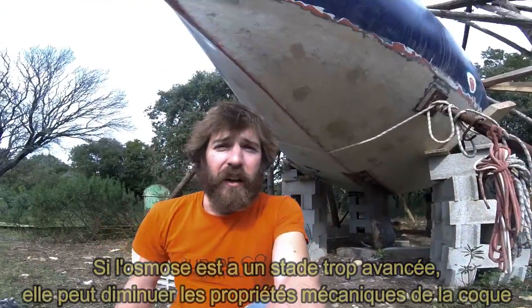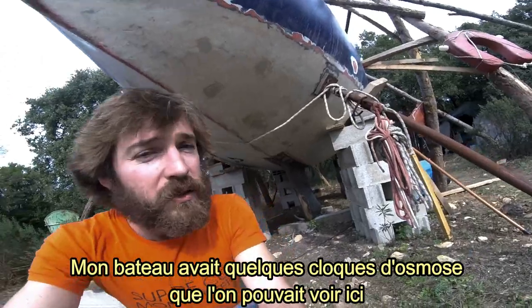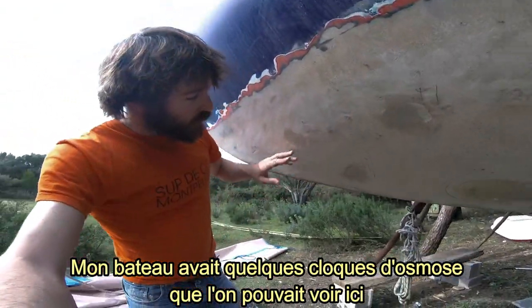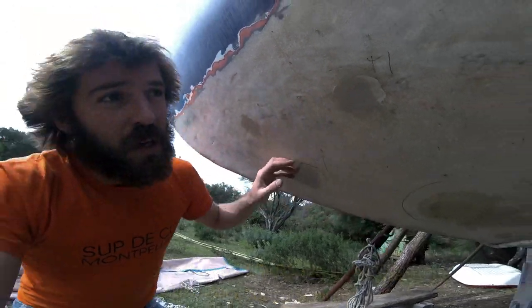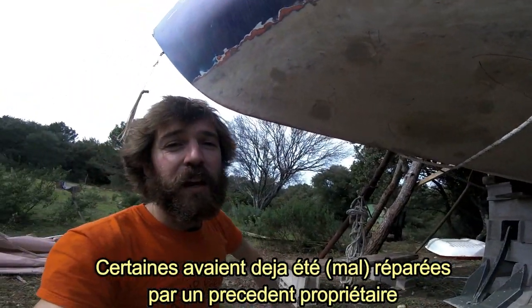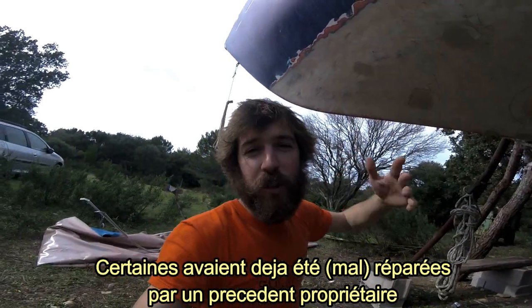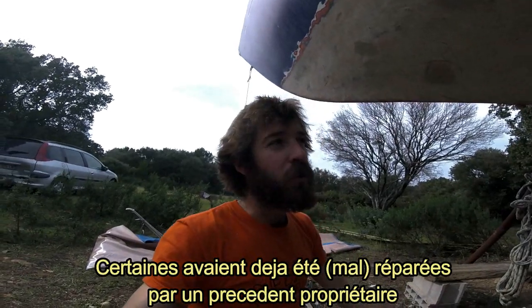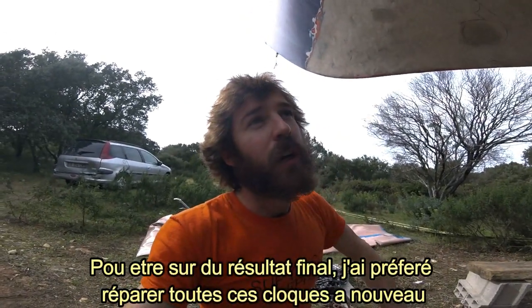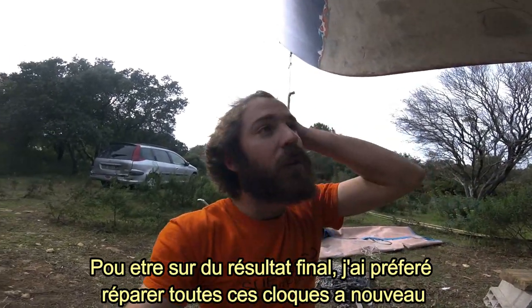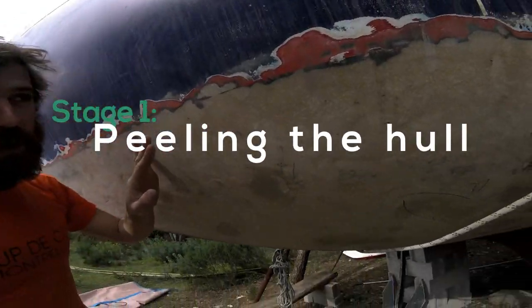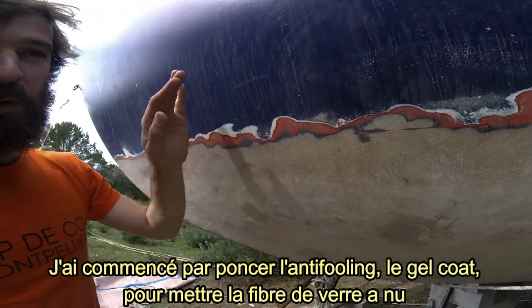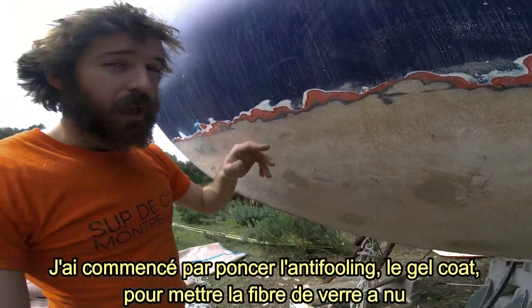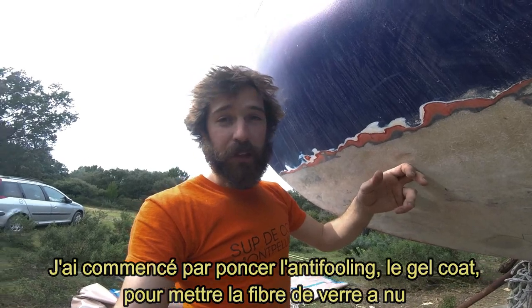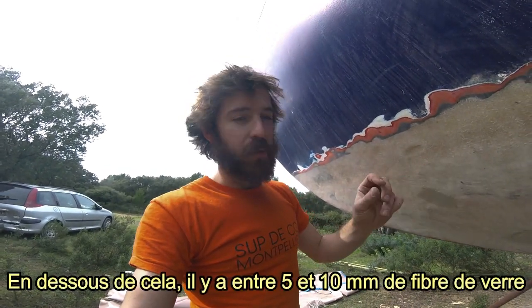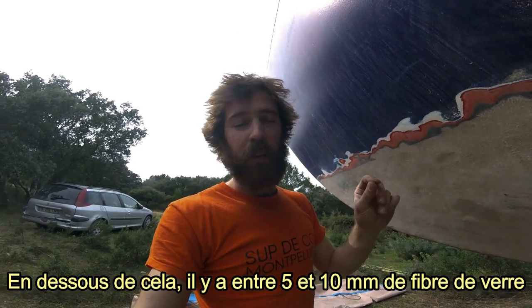So basically I had a little bit of osmosis on my boat, which you can see when you go under it. There were little blisters in some parts. Most of them were already fixed in a previous treatment that was not done properly, but just to be sure and to have a nice hull, I preferred to treat all these blisters again. First I peeled the hull to the fiberglass, which means removing the anti-fouling and the gel coat, going to the fiberglass. Below this there is between 0.5 and 1 centimeter of fiberglass.